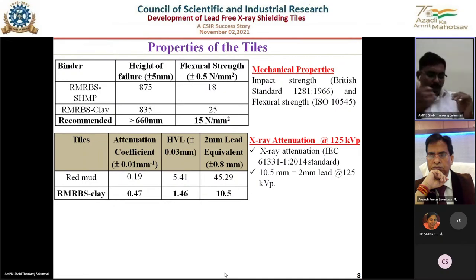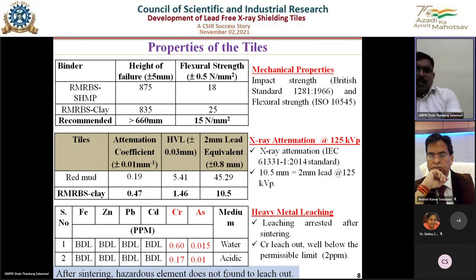So wherever hospitals are having X-ray diagnosis or CT scanner rooms, normally they are using 2 mm lead sheets. So instead of that, we can use 10.5 to 12 mm thick red mud based radiation shielding tile. And as I mentioned, red mud is also considered to be hazardous because of its heavy element leaching.